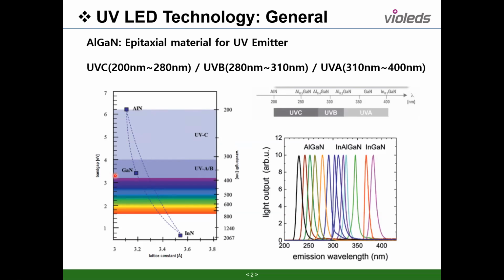And then under 300 nanometer, around 260, it becomes lower than 3% actually. So currently the efficiency of the LED is very low. However, in the future, I think it will become more than 10, 20%, and then it can replace all the mercury lamps with LEDs. So if you are considering using LEDs, then I think it's a good time to try, and then you will see how it improves together with your technology.